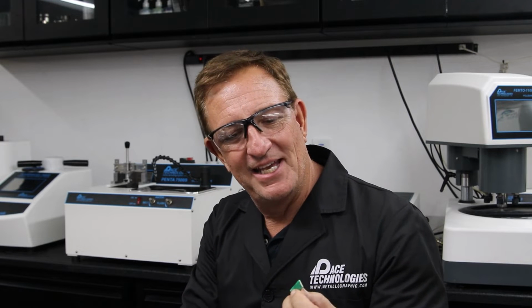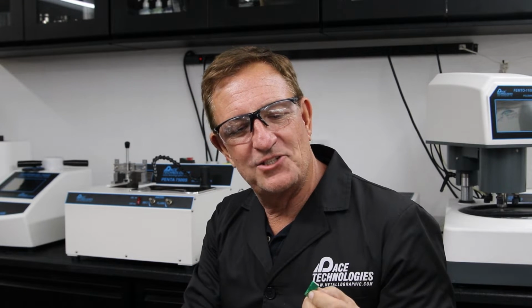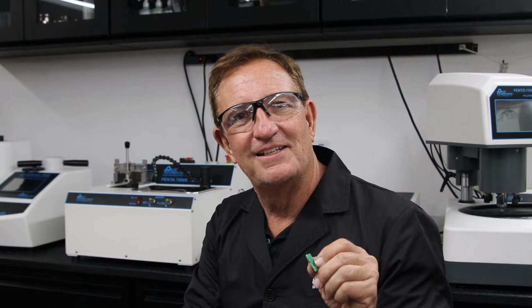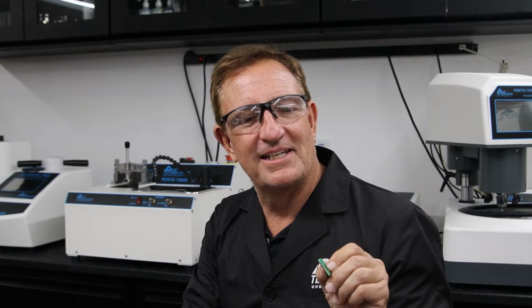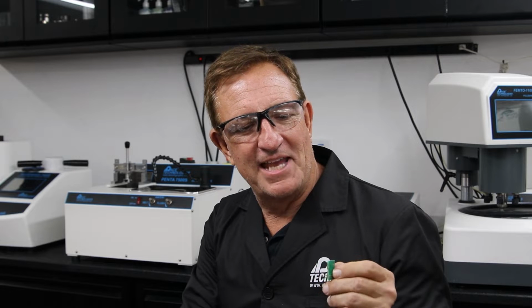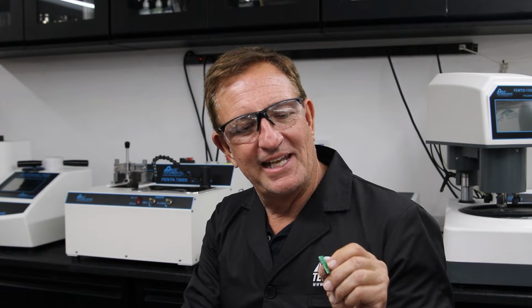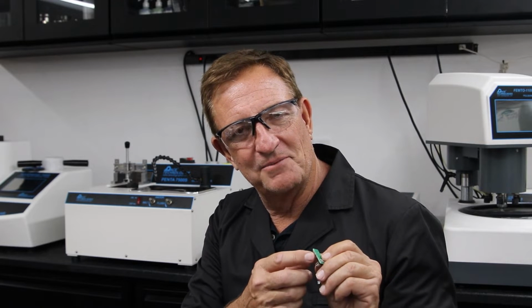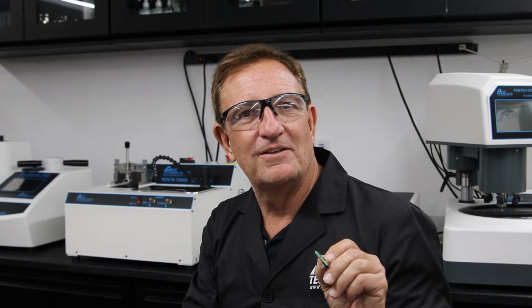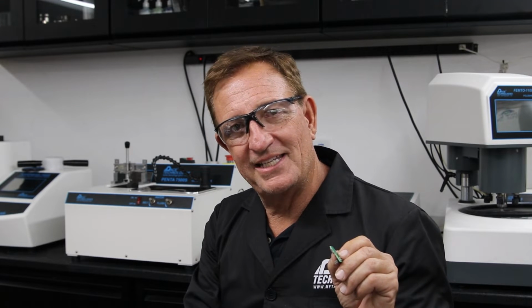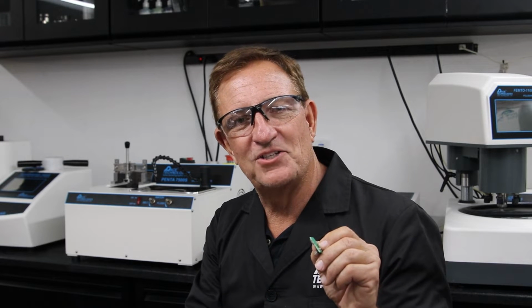Vacuum impregnation. Why would it be useful? Let's discuss that in a little bit more detail. Vacuum impregnation essentially allows us to fill in voids or gaps that occur in our sample. For example, here's a PCB board, and after we cut it, we can see that there are some layers that are just open air. If we want to grind this and not deform that during the grinding and polishing operation, we actually want to fill that with a castable mounting resin.